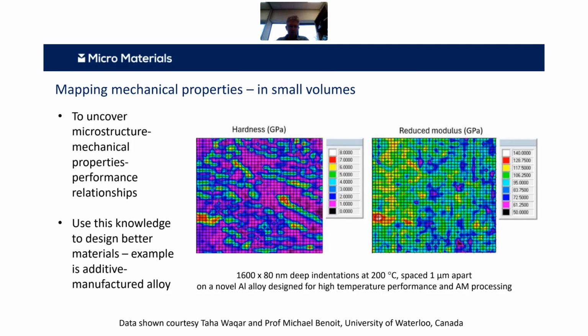So what you can see here is 1600 indents. They're all the same depth. They're spaced 1 micron apart, so the geometry of the probe limits how many you can do. And what you can see on the left there is essentially a multi-phase material with lots of features through that structure of high hardness. But you can see on the right that it's a slightly more smeared out pattern when you come to the elastic modulus in the material.